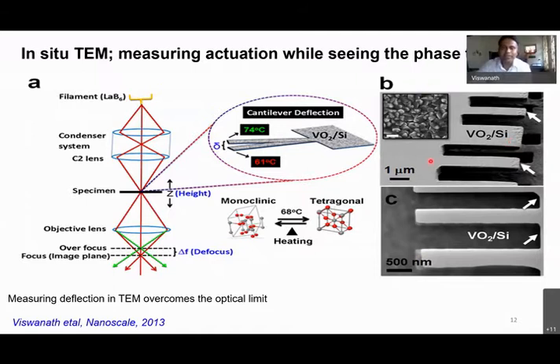It is inspired by the several negative results, because I want to actually see during the phase transformation, is there any twinning? I was trying to take bright field images as well as high resolution images. During the phase transformation, what I found, the imaging is almost next to impossible. You will see everything is perfectly in focus. The moment the phase transformation starts, suddenly the sample just goes out of focus.